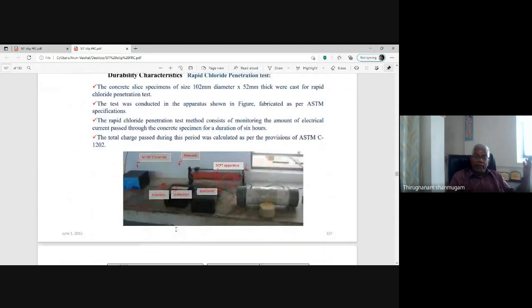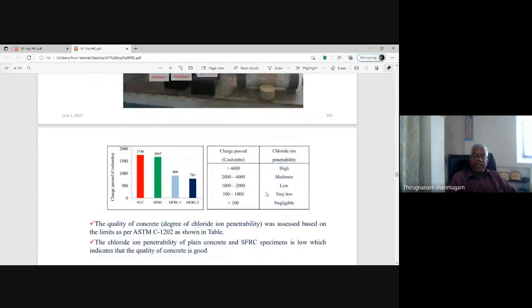Similarly, these hybrid fiber reinforced concrete specimens are subjected to a durability test, the RCPT test, rapid chloride permeability test. That is the cylinders, NaOH solution and NaCl. That is the specimen, 52 mm thickness specimen. And the electrode is placed and 60 volt current is passed. Every 30 minutes, the Coulomb readings are taken and total charge passed is calculated, and we obtain the results.